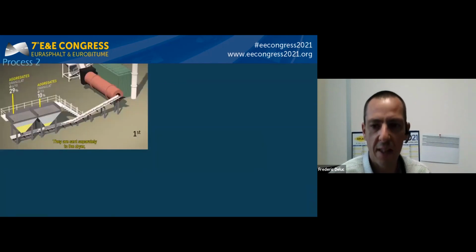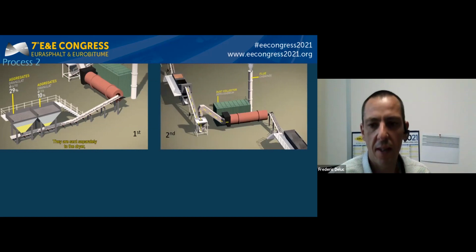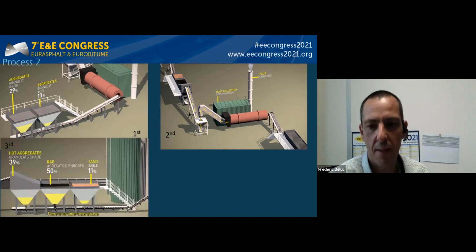The second process consists of heating the aggregate in a dryer drum. This heated aggregate is then transported to the cold manufacturing plant. It is then mixed with RAP, sand at ambient temperature, and emulsion in order to manufacture the semi-warm mix, which is also at a temperature of between 50 and 100 degrees.